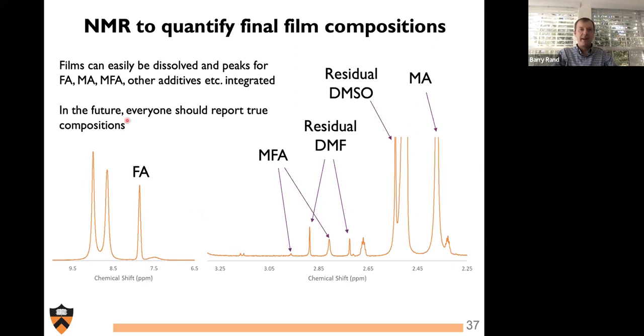Films that are produced and the ones that are ultimately used for devices can be easily dissolved, and you can integrate each of these peaks and determine what is left behind. Here we have an FA and MA containing film, which has residual DMSO, residual DMF, and also has MFA there. And so we can use this to really quantify what's there in our film. And I think this type of reporting will lead to an eventual maturity of this Perovskite research community.